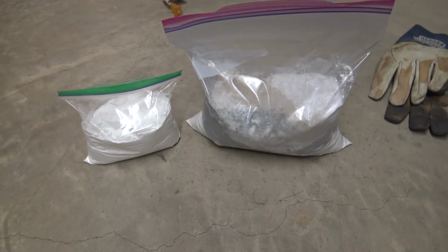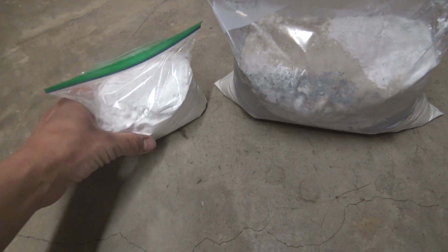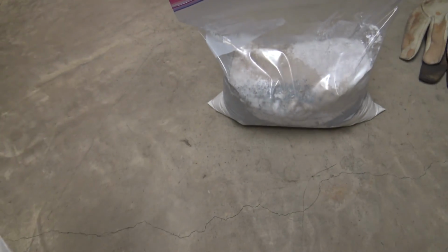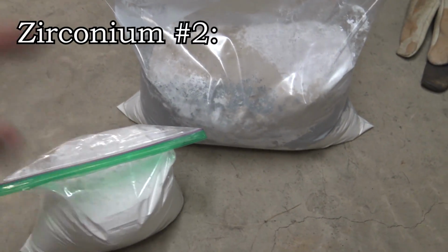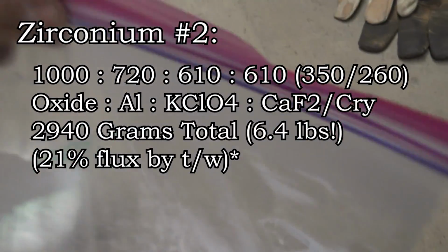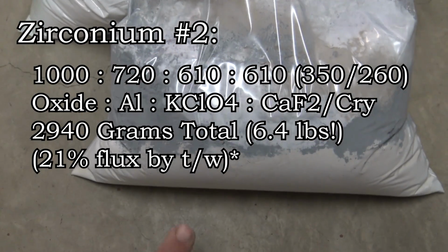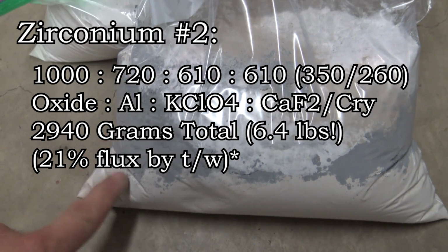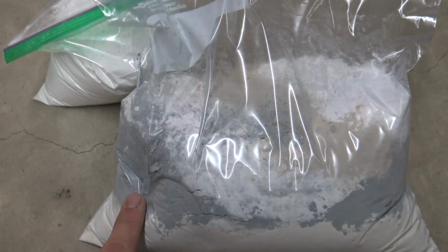Because I originally bought 5 pounds of the zirconium oxide, there was a lot left over after the last reaction, and because I want to see if it'll grow the same type of crystals again, let's do another. This one uses the same formula as the last one, but I scaled it up from 456 grams of the oxide to 1,000 grams. Let's mix it up and take it outside.